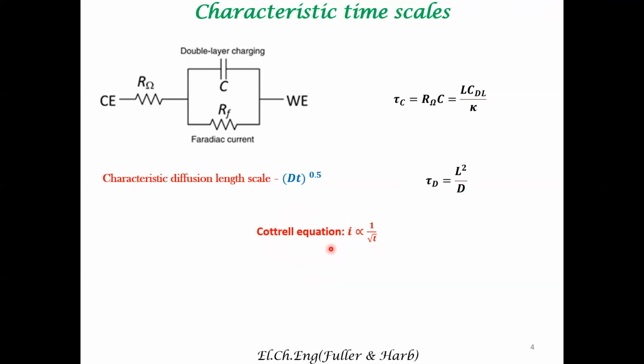Why is that so? The reason is that if you plug in the characteristic values from experimental data, the conductivity, double layer capacitance, and the characteristic length scale, what you observe is that the time scale for diffusion is much larger than the characteristic time scale for capacitative charging. It is only at very short time scales that the capacitative current plays a role. Under long time scales, it is only the diffusion that plays a role. So that is the reason why, when we derived the Cottrell equation, we completely neglected the capacitative current.